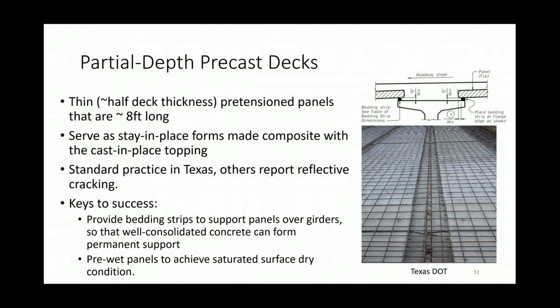So one is the partial depth precast deck panels. These are essentially like stay-in-place forms that may be pre-tensioned, about half the deck thickness, and they provide a safe walking surface and formwork, essentially. So this one we heard quite a bit from Texas DOT, because this is apparently more than 90% of their bridge decks are built this way. So this is essentially standard practice to use stay-in-place or partial depth precast deck panels for their deck construction.